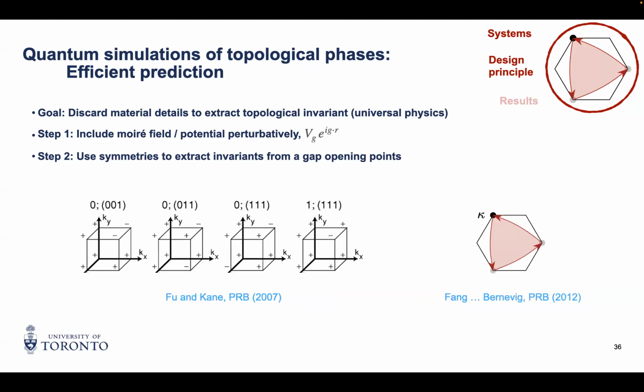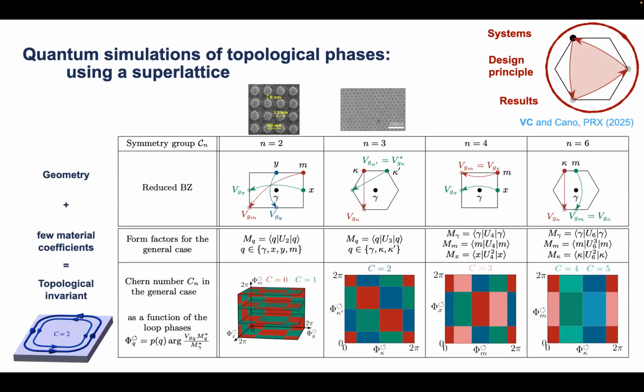And from that, I can get the Chern number. So mathematically, this is described by something that we call topological symmetry indicators for topological invariants, right? And it allows you to get a phase diagram like so. So it's too much information, but basically, if you followed what I've said so far, from the harmonics of the superlattice potential and a few material coefficients that I combine as a product, I can get the Chern number of the system composed of the 2D monolayer, the Chern number of the mini bands for the system composed of a monolayer and a superlattice potential.